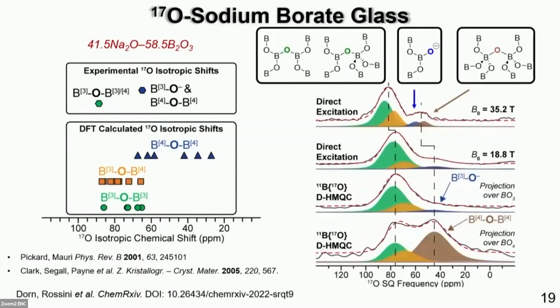Now, I do also want to share this. We just very recently recorded a 1D oxygen NMR spectrum at 35 Tesla using the SCH at the high field lab. And what we can see is that we almost can start to resolve out this oxygen atom that is bridging between two BO4s from the non-bridging oxygen, where they are completely overlapped at 18.8 Tesla.